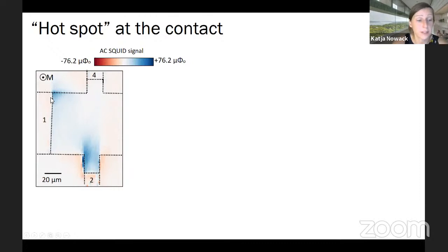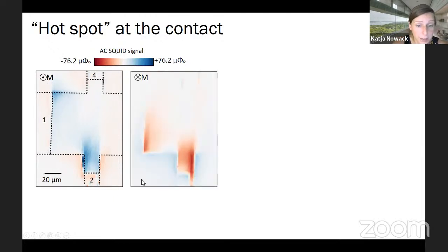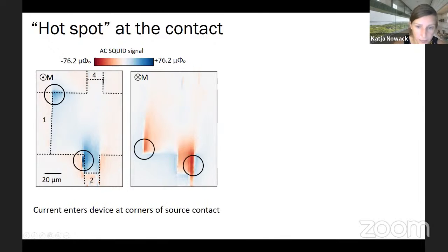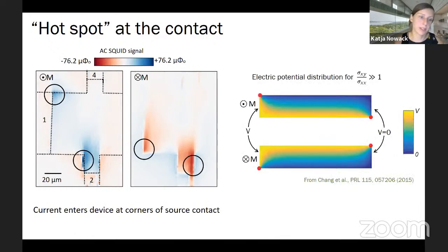And I should point out, this is taken at a backgate voltage at which we have fully quantized transport coefficients. If we flip the magnetization of the device, now the current actually enters in the different corner of the source contact. And I should point out the current is actually sourced from contact 1 here, and is drained in this voltage probe. And so that's why you also see strong flux signals in this contact here.